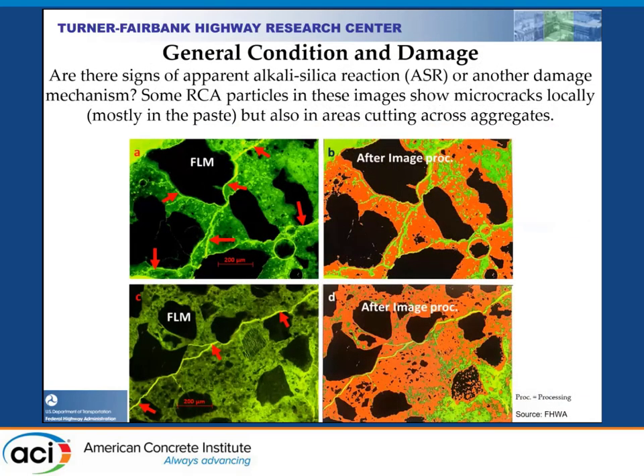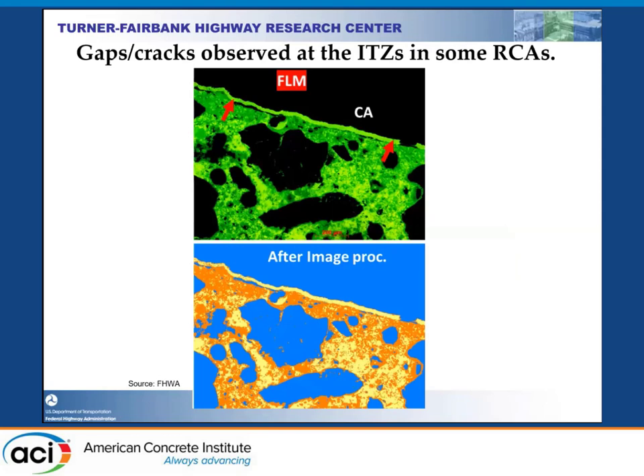For general condition and damage assessment: are there signs of apparent ASR or another damage mechanism? In photomicrographs of thin section images, some RCA particles may show microcracks locally, mostly in the paste but also cutting across some aggregate particles. Regarding gaps at the ITZ: as seen in the after-image-processing image, you can clearly see the gap at the paste and aggregate interfaces.